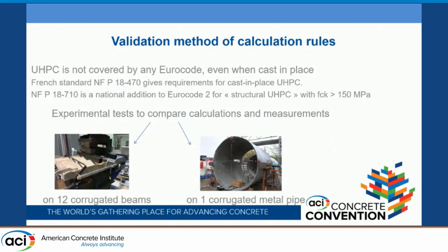UHPC is not covered by any Eurocodes, even when cast in place. The French standard gives requirements for UHPC cast in place. And we also add a national addition to Eurocode 2 for structural UHPC with a minimal compressive strength of 150 MPa. Through the experimental program, we compared calculation and measurements. On the one hand, one specific test body to validate the calculation method, and on the other hand, a scale 1 test specimen to validate the expected mechanical functioning.